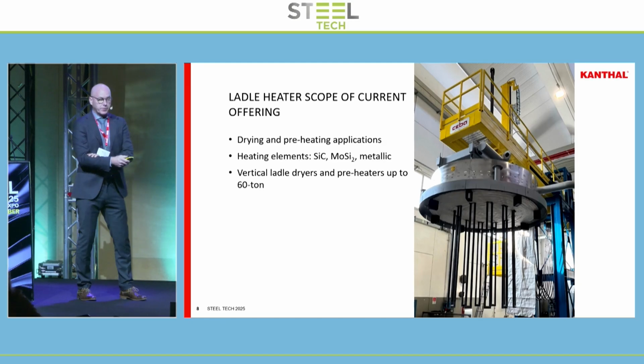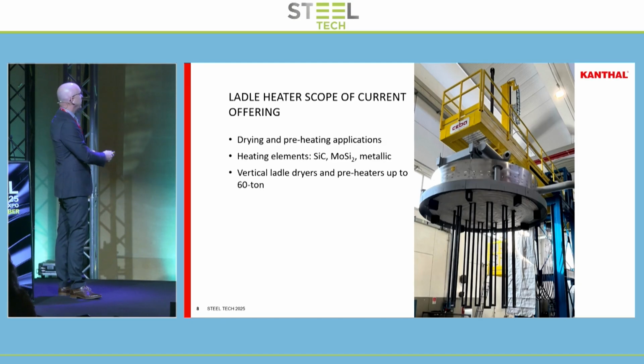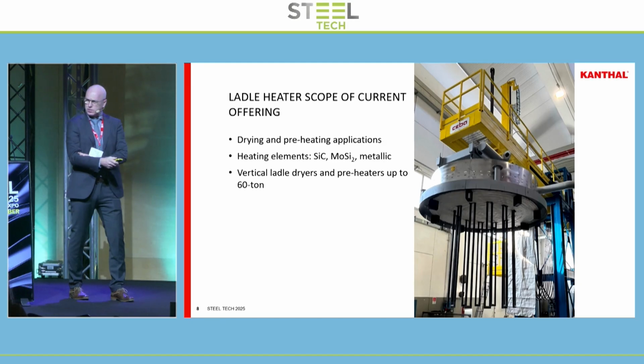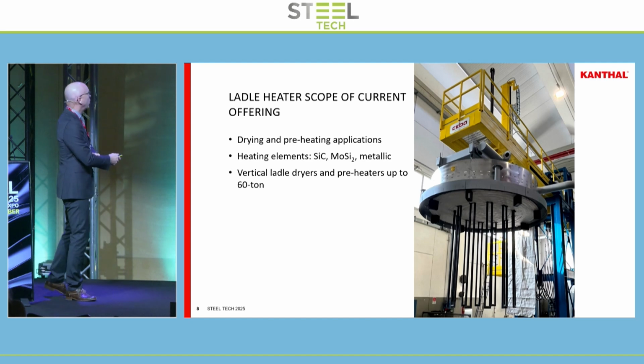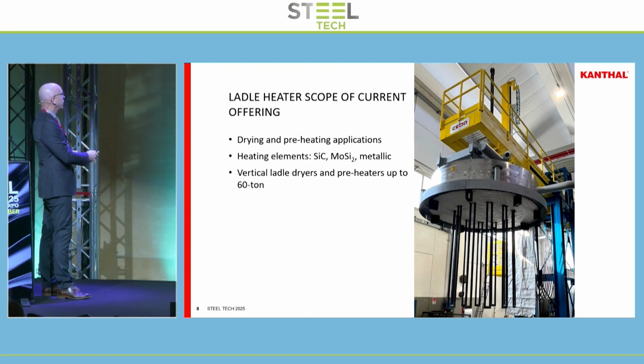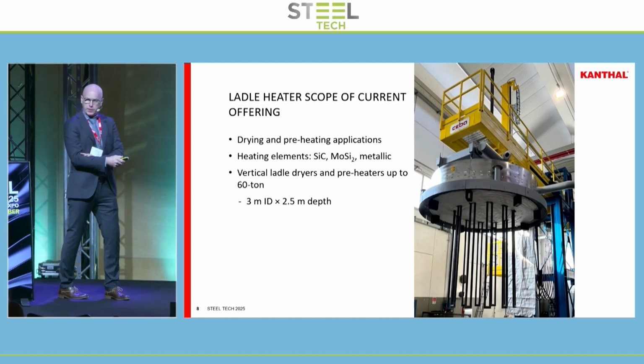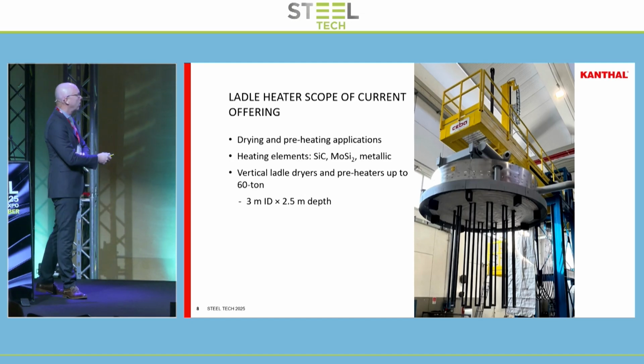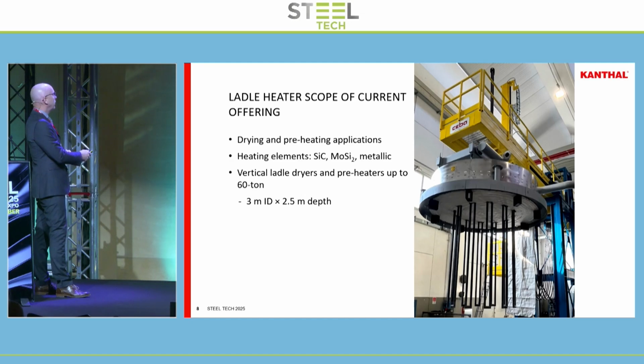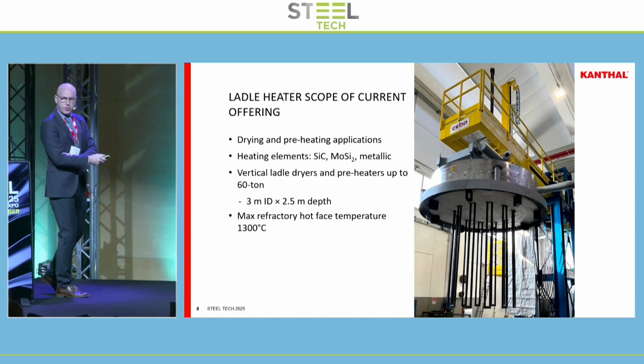So far, we developed and delivered preheaters up to about 60-ton ladle size. So it's going up in scale. We see progress there, and looking at that, it's about a 3-meter inner diameter ladle, and pretty deep. So you say a max refractory temperature of about 1300 degrees there.